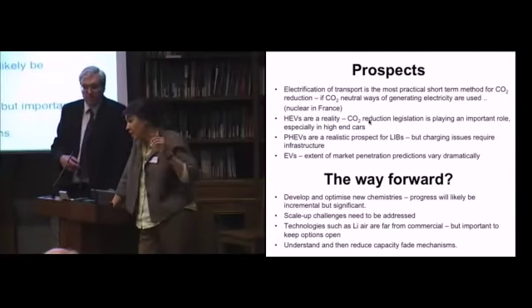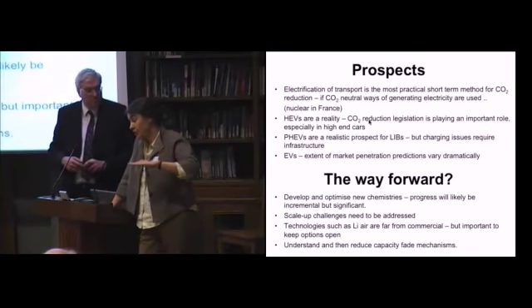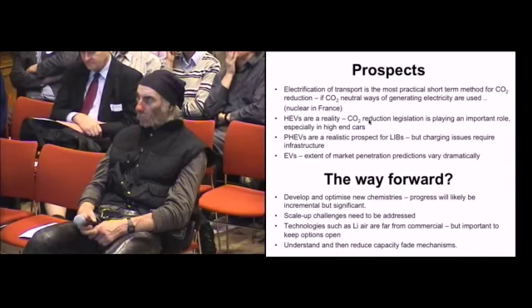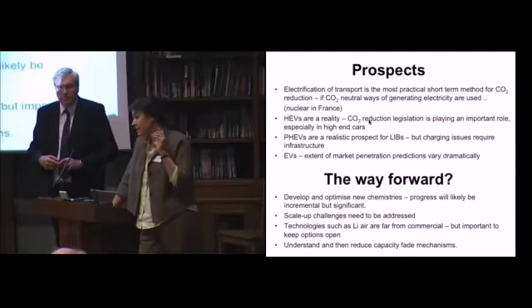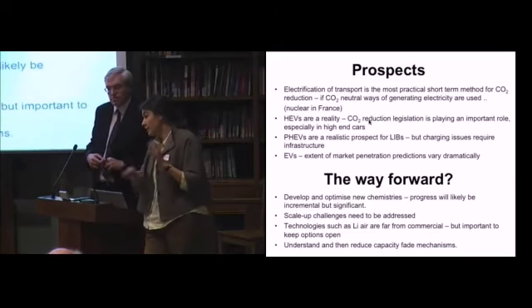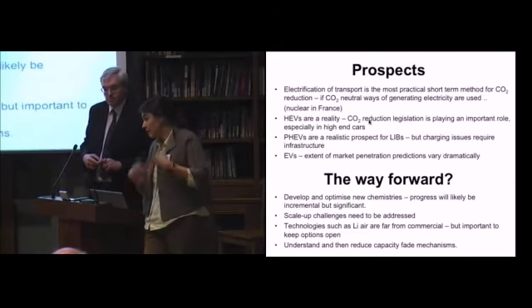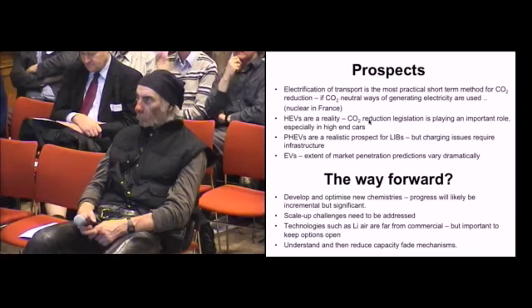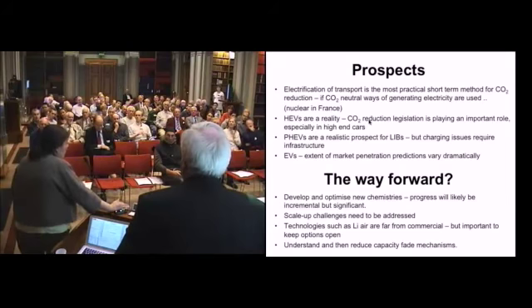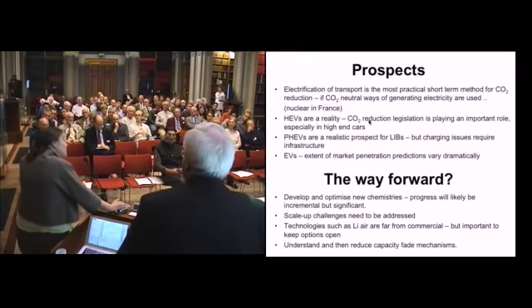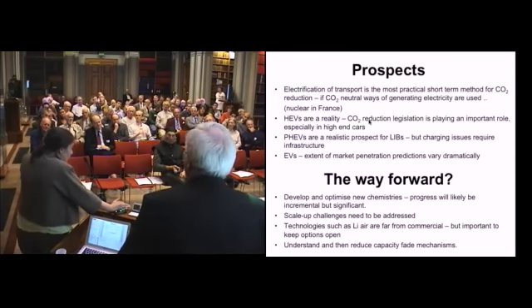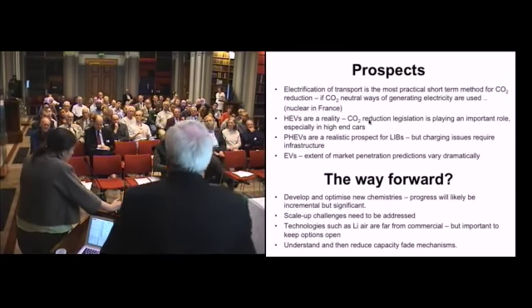So you can replace carbon by a lithium titanate, and you up the voltage from just above 0 for carbon to about 1.5 for lithium titanate, and that is a very fast material, but it's considered a safe material because you don't plate lithium, because your voltage is that much higher on the anode side, and so you can push it faster. It has limitations because it's got a much smaller voltage. So there are some companies that are pushing it, but it's also got side effects. It's not as stable as people used to think. Most companies are not putting the titanate in there, but it is one of the materials being considered. But because you're going from almost 0 to 1.5 volts, you're reducing your battery from about 3.5 volts almost down to 2 volts. So there are pros and cons.